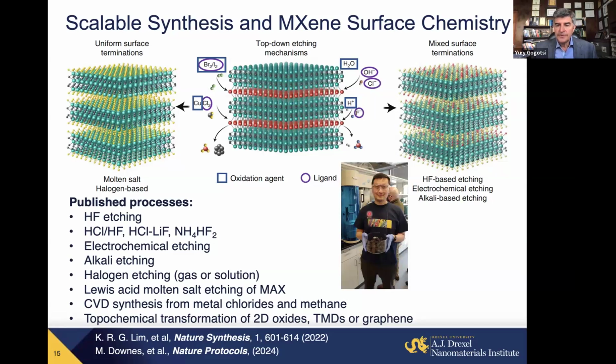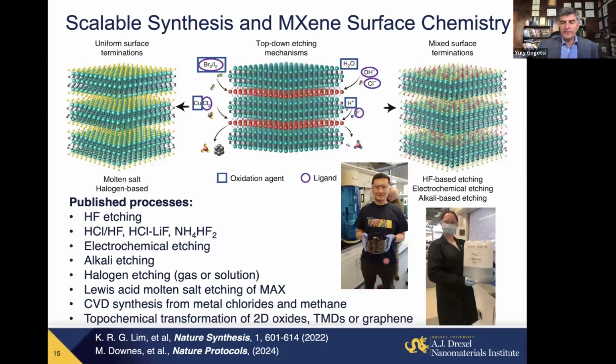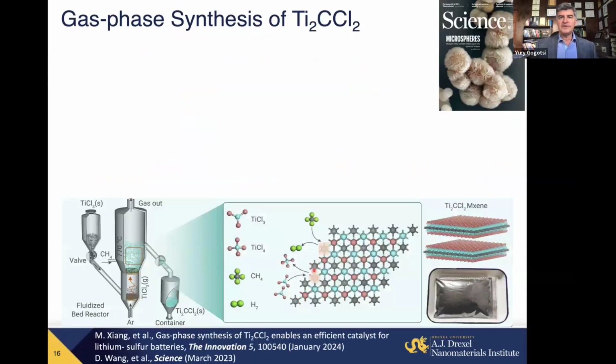Here is my postdoc, John Wang, holding 1 kilogram of MXene produced in our laboratory, titanium carbide. And here is my undergraduate student, Marley Downes, holding probably about 8 liters of dispersion of niobium carbide, Nb2C MXene flakes in water. So what it means is that you can make these materials in quantity. So it means that applications are not limited to exotic electronic or optical devices. They can be used in water desalination, energy storage, energy generation, thermal management. As the application, a large amount of materials is needed.